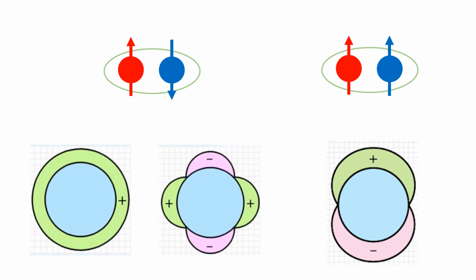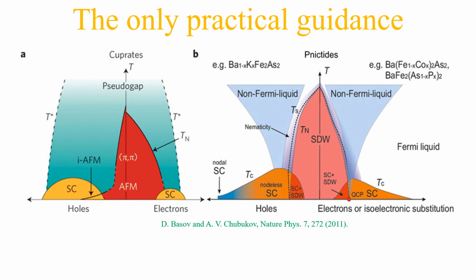So how do we look for another spin-triplet superconductor? To be honest, we don't even have a good guidance to look for a conventional superconductor, let alone an unconventional superconductor with triplet pairing. That being said, we do have some practical guidance. If we look at the phase diagram of two high-temperature superconductors, cuprate and iron-based superconductor, they obviously share similarities. The parent compounds are not superconductors, but have an antiferromagnetic ground state. When the antiferromagnetic ground state is suppressed, either by chemical doping or pressure, superconductivity emerges.